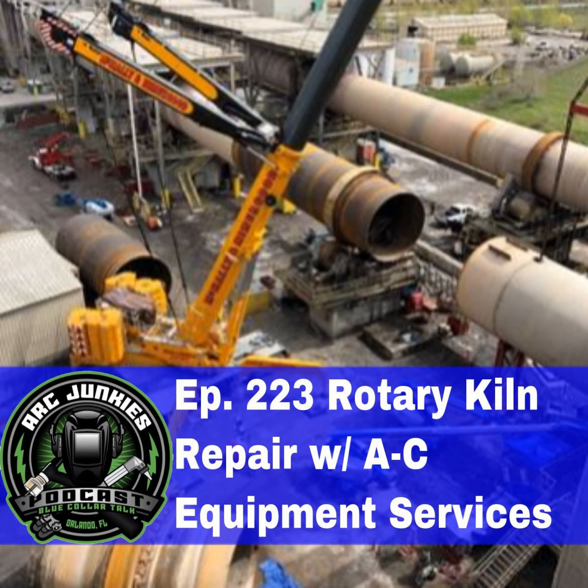And if you get lucky, that kiln's at ground level, but 90% of the time it's 35 feet in the air or higher. Okay. So then you're on the inside of it, 100 foot up in the air, back gouging out the sound weld metal and then putting another weld pass on the inside. That's correct. Now, typically it's a several day process of fit it, seal pass it, subarc weld it, back gouge and weld the inside. And we typically find ourselves about half of the time getting our weld joints ultrasonic tested to meet D1.1 standards.